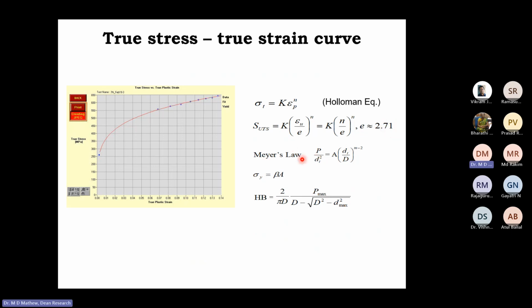And applying Meyer's law, you will be able to determine the yield strength of the material using a relationship where yield strength is equal to beta into A. Again, the hardness also can be derived through an equation like this. I'm not going into the derivation of these equations. All I want to tell is that from the load and depth combination data, we are able to get true stress, true strain data. From that, you are able to determine the yield stress of the material, ultimate tensile strength of the material, as well as the hardness of the material.